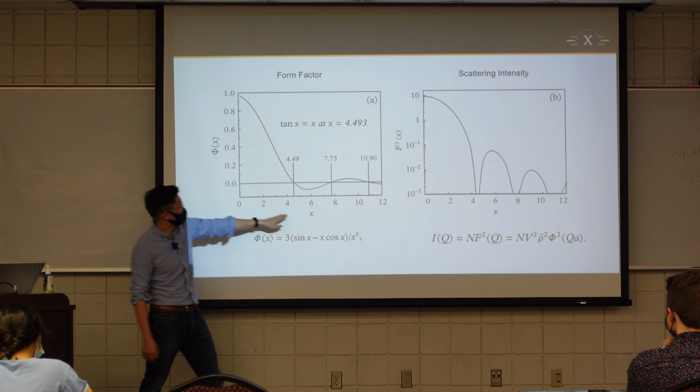And what would the intensity equal to? N is just the number of electrons. This will not change the shape, but it will change the height of it. So for an electron-dense material like gold nanoparticle, compared to polymer nanoparticle, we're going to scatter more because there's more electrons in the given volume. So your intensity will be higher. You tend to get better statistics, or you can lower your measurement time without sacrificing the data quality, okay?